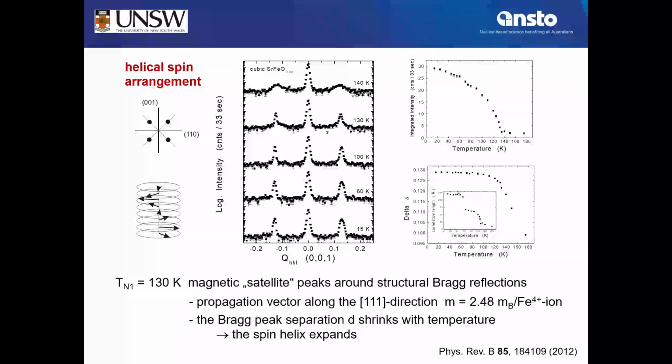So what do we learn from that? The distance here, delta, is directly 2 pi over a, in K-space the length of 1 full rotation. So the pitch length. So we know exactly how long it takes for 1 spin rotation.